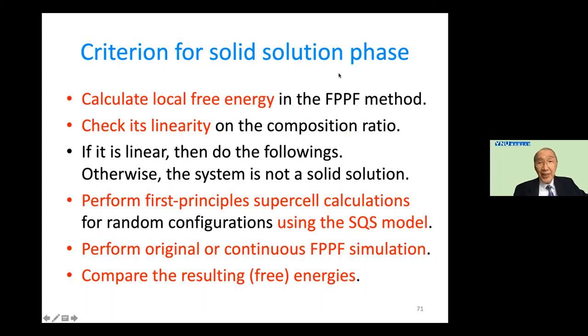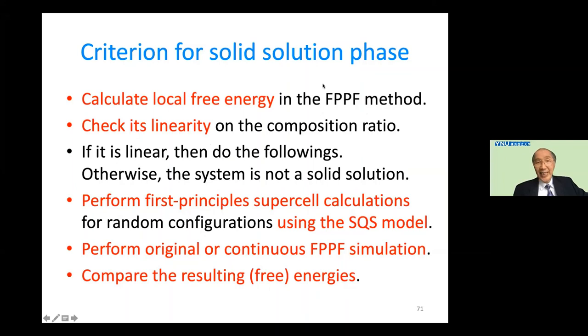The criterion for a solid solution phase is: calculate the local free energy in the FPPF method and check its linearity on the composition ratio. If it is linear, perform first principle supercell calculations for a random configuration using the SQS model, run the continuous FPPF simulation, and compare the resulting free energies to judge whether the alloy is a solid solution or a two-phase coexistence.